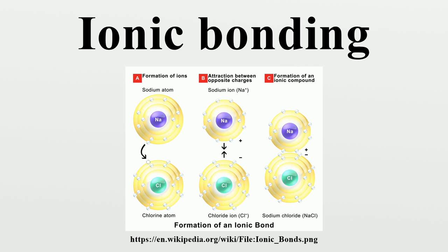Bonds with partially ionic and partially covalent character are called polar covalent bonds. For example, NaCl and MgO interactions have a few percent covalency, while C–O bonds are usually 50% ionic and 50% covalent. Pauling estimated that an electronegativity difference of 1.7 corresponds to 50% ionic character, so that a difference greater than 1.7 corresponds to a bond which is predominantly ionic.